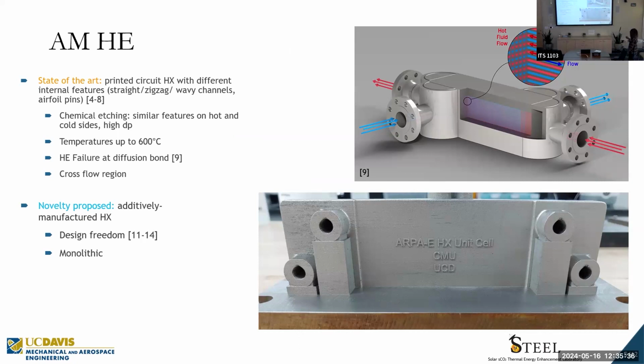And so what happens when we fabricate these, we start with a solid plate. We chemically etch the channels. So you can see here it has a set of, red for hot channel, blue for cold channel. We chemically etch these channels. We repeat this process for several plates, and then we stack the plates together. Then we apply pressure and temperature to diffusion bond the core of the heat exchanger, and after that we weld the headers on top of it.